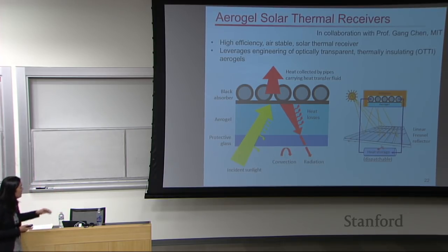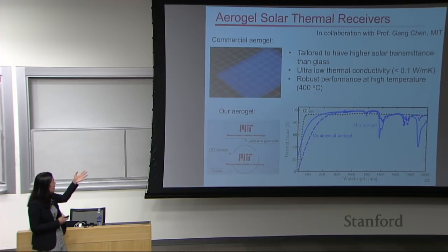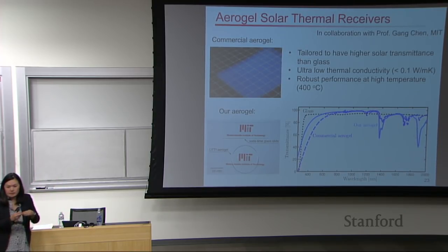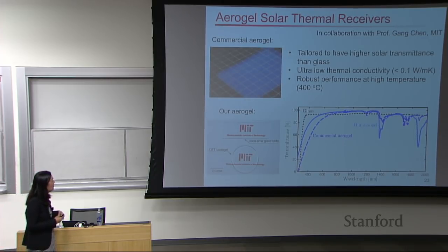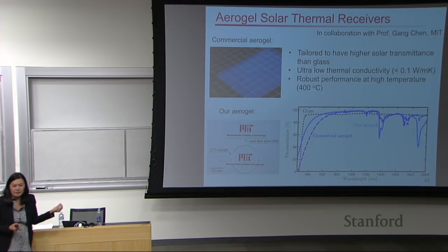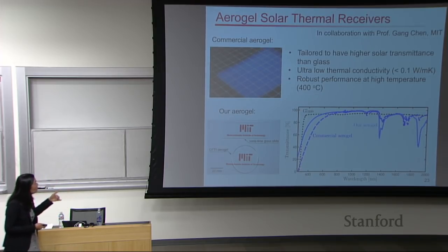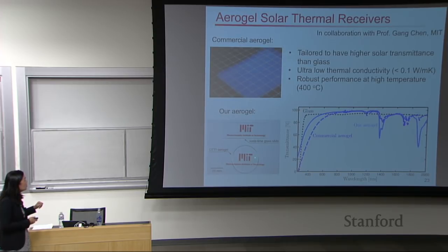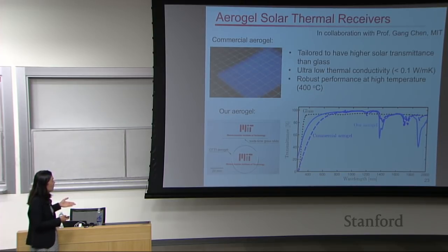So we've been working on this for some time. And as I mentioned, the key idea here is that we would need to create these aerogels that are optically transparent. And traditionally, when you think about commercial aerogels, they usually have this kind of bluish tinge to them. Right? And it's because of the scattering of these silica bead type structures. And what we've been working on is really fine-tuning the structure itself and being able to control the distribution of the pores of the aerogel, and to also decrease the size of the features such that we can minimize scattering. So through the support of RBE, what we've been doing is, in fact, now being able to create what we call these optically transparent, thermally insulating aerogels that look almost just like soda-lime glass, right? You can see from the transmittance measurements as a function of wavelength that they're far superior to that of commercial type aerogels in this case.